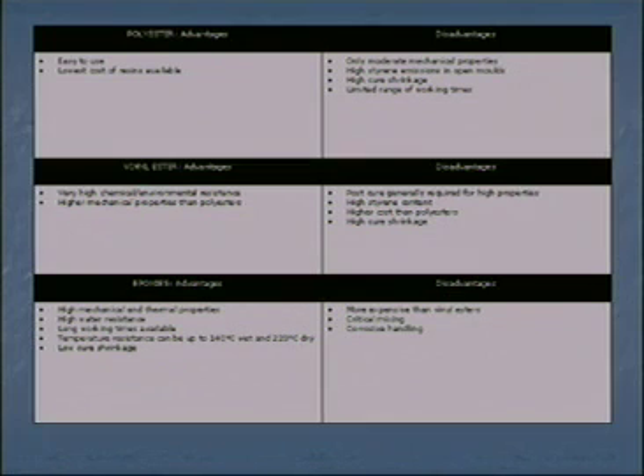Some of the advantages and disadvantages of different resins, the top is polyester. So the advantage of polyester is that it's easy to use and it's very cheap, so it's a low-cost resin. Some of the disadvantages, only moderate mechanical properties, so it's not extremely strong, may crack. High styrene emissions, so what that means is it's going to put a lot of styrene out into the air, which isn't really good to breathe. High cure shrinkage, so it's going to shrink as it cures. Like that video said, they showed that the clear resin, after it cured, shrank away from the mold. So it does shrink some. And then it has a limited range of working time. So you're really stuck with that 7 to 10, 15-minute range. You don't have much more working time than that to work with it.